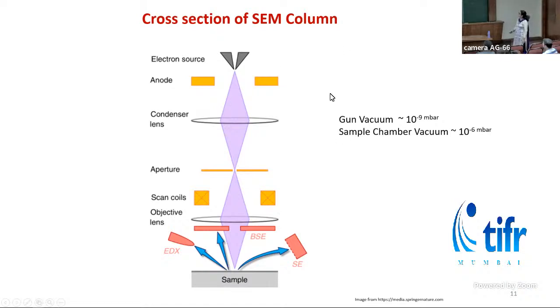But here is a cross section of the SEM column. So this is the electron gun, which can be tungsten or FEG, anything. It is accelerated downwards by these anodes. Then it has electromagnetic lenses. The first lens is the condenser lens. It focuses the beam into a fine spot. This lens also decides the current in the beam. Then there are apertures which eliminate the off-axis electrons, and there are scan coils because we need to scan the sample, and the objective lens is the final probe-forming region.